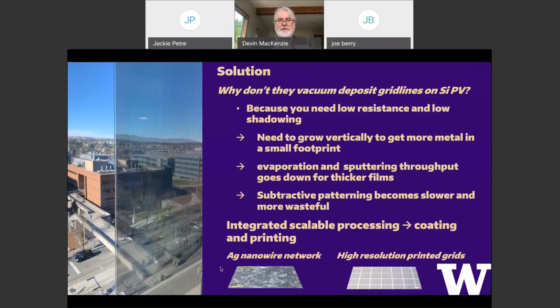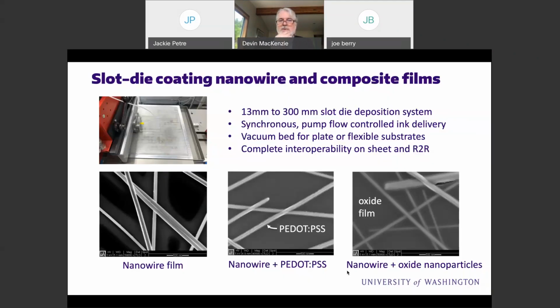So there are approaches to solve this. One is a network of nanowires that are percolated, interconnecting, or we go to intentionally high-resolution printed grids. We touched on both of those. We developed slot die coated nanowire composite films. The nanowires are readily synthesizable and makeable, and they work. They work actually pretty well, surprisingly well.